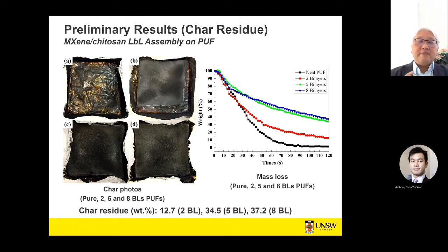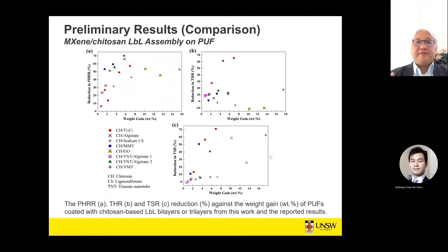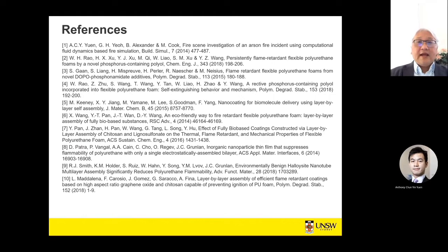And if you look at the mass loss itself, with the 8 bilayers it still retains at least 40% of the material remaining behind, while a foam without flame retardant basically burns all up by 60 seconds. And these are the references that I've done.